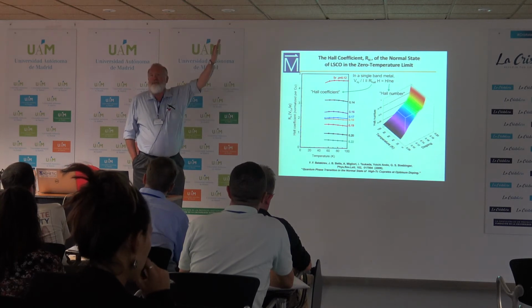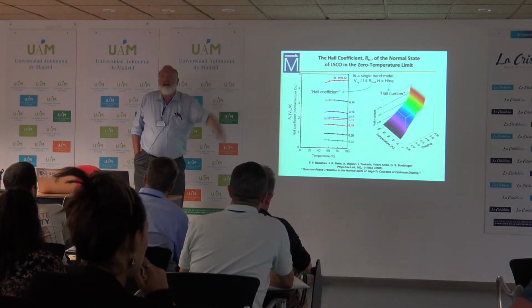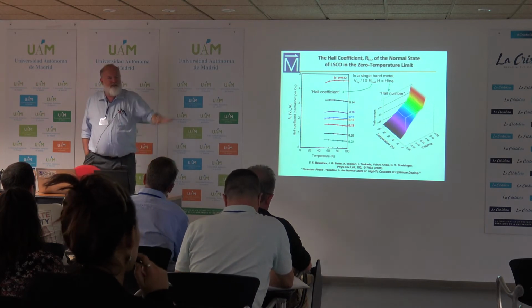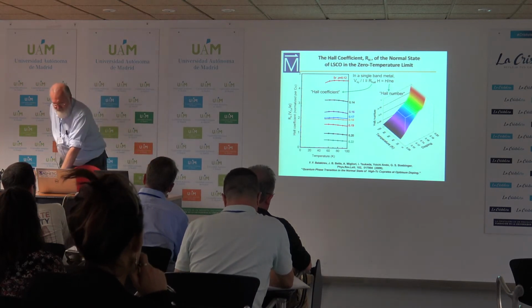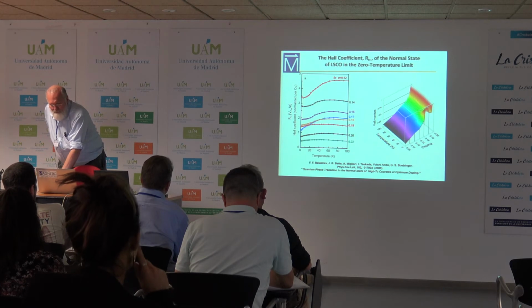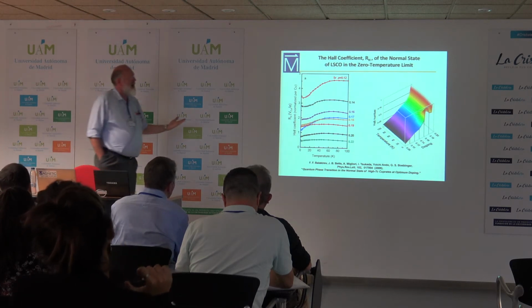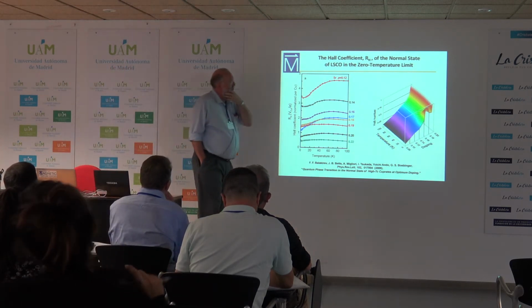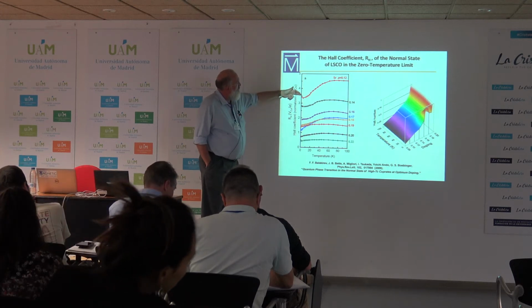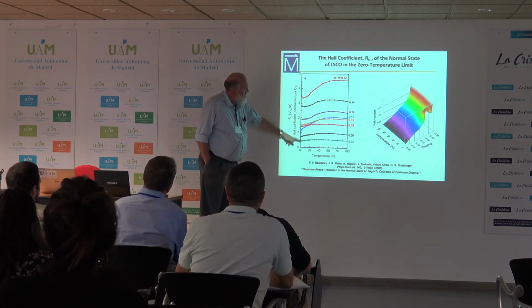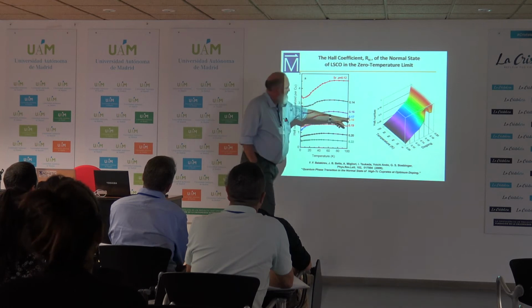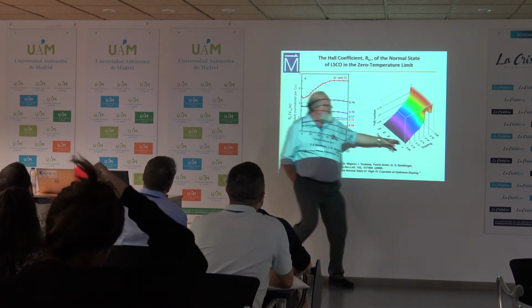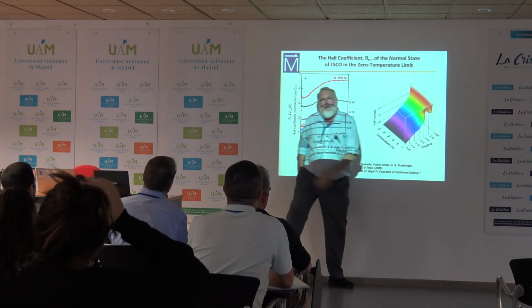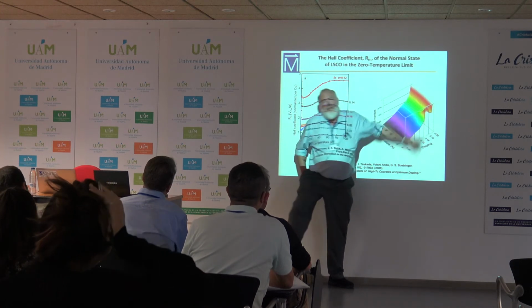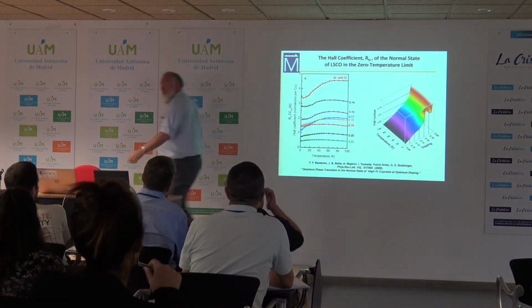We know that there's going to be a divergence to positive infinity as you go into the overdoped regime, because eventually your band curvature changes. But the important part of this result comes when you use a high magnetic field to suppress the superconductivity. And then no longer is your Hall coefficient monotonic. Here at the 0.17 you see it crosses, and that's what gives you this non-monotonic behavior at low temperatures that you cannot see when the superconducting phase is in the way.